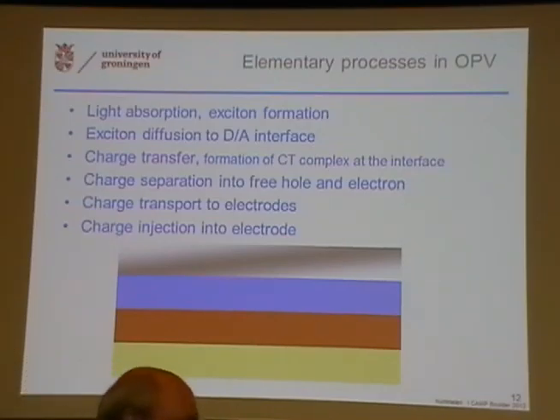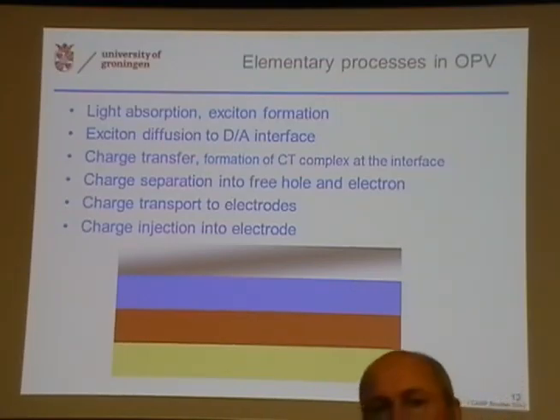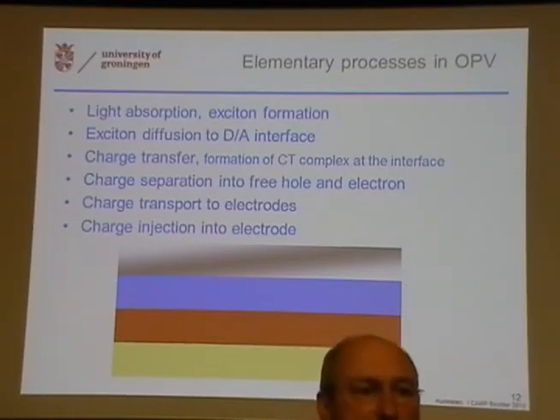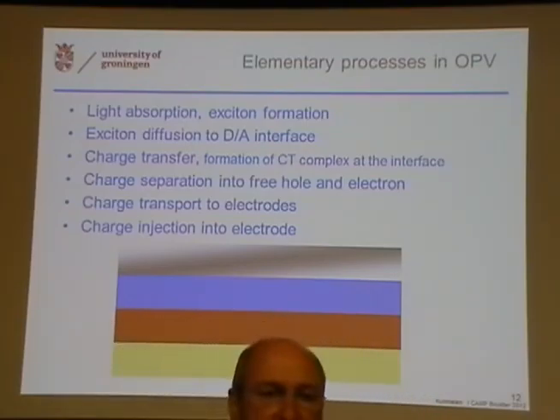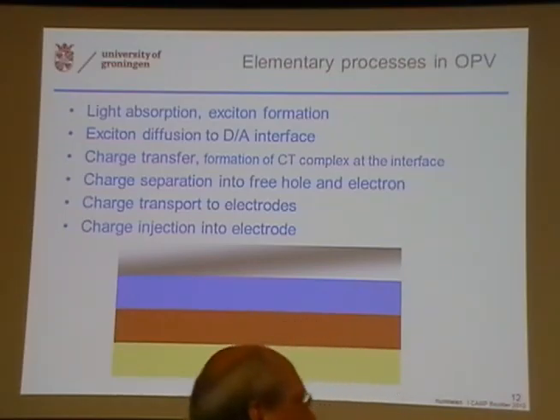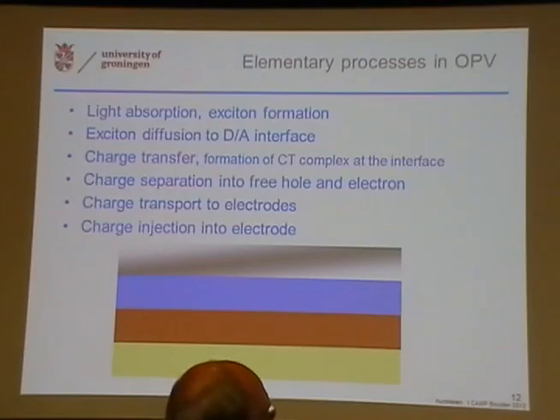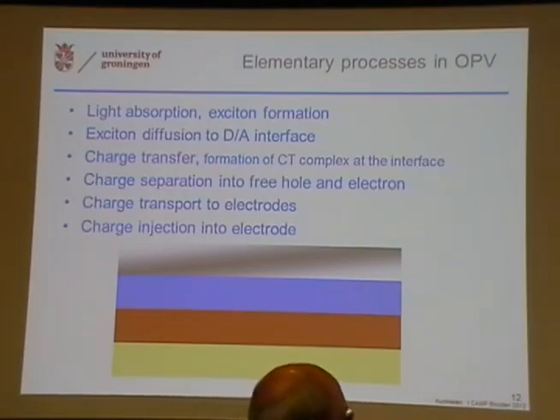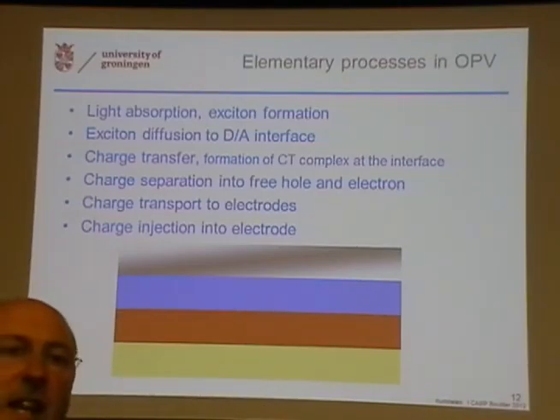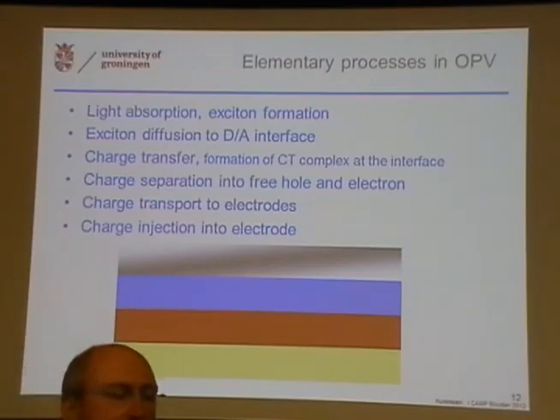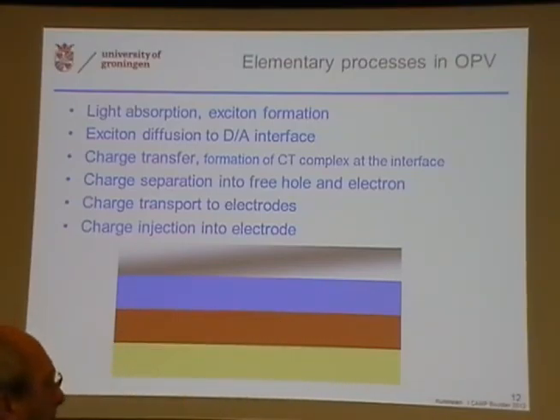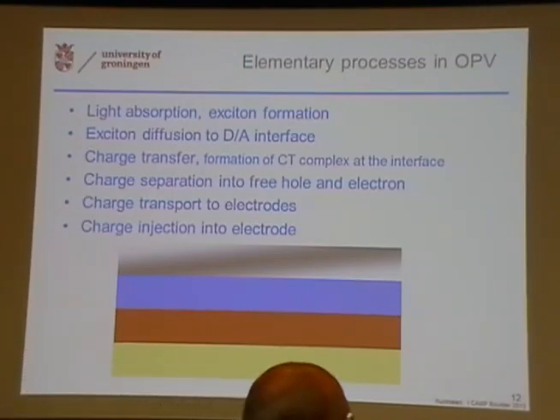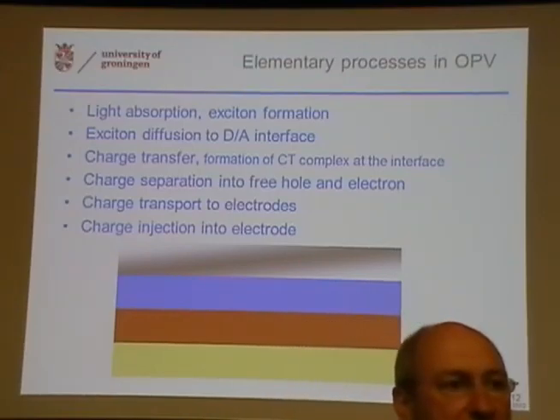Then this excited molecule, this extra excess energy, has to travel to the interface of a donor and an acceptor, because the charges are Coulombically bound. They don't separate spontaneously, like in silicon. So you have to use a second material with either a higher affinity or a lower affinity, we come to that, and then you can have charge separation, charge transfer. This can be hole transfer or electron transfer, depending on which one is excited. We have formation of a charge transfer complex, maybe, not always, and then the next thing is that you have to separate those charges, and then you get the free charges. The free charges have to drift and diffuse through the materials and get into the electrodes.